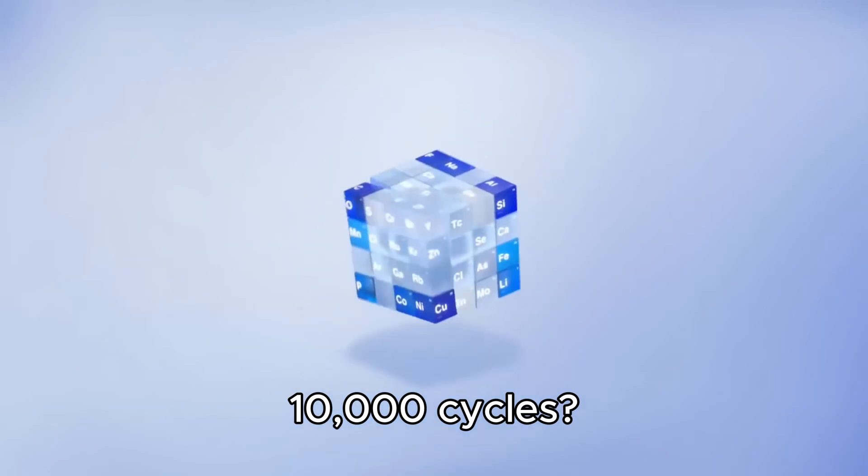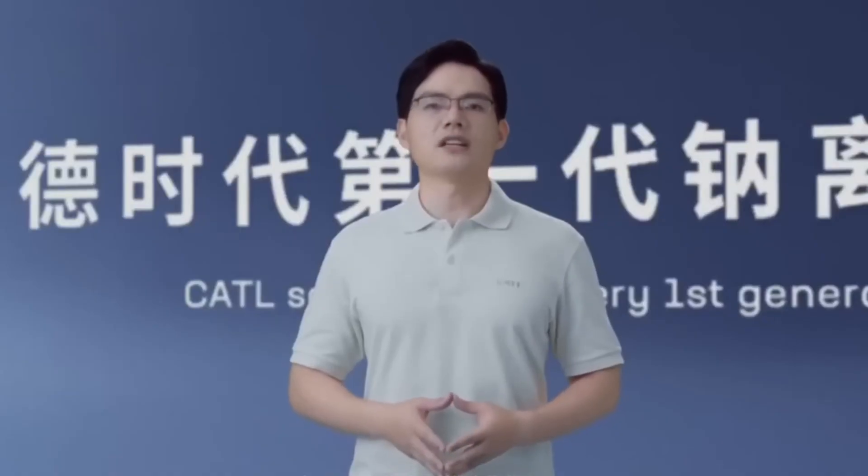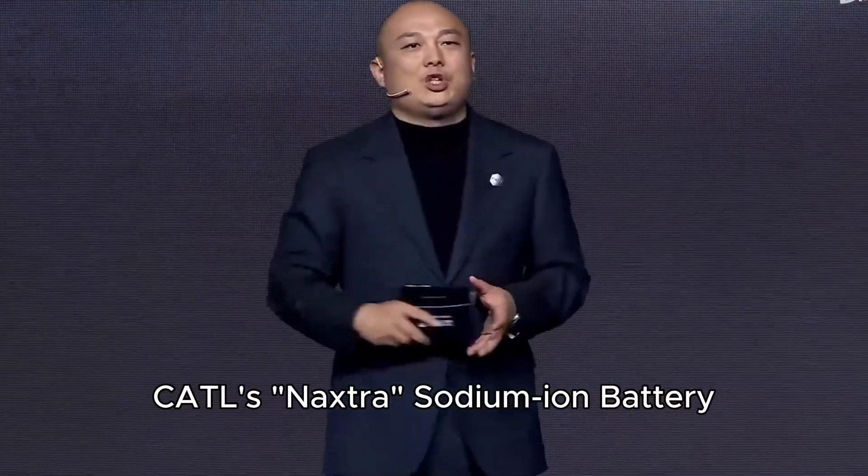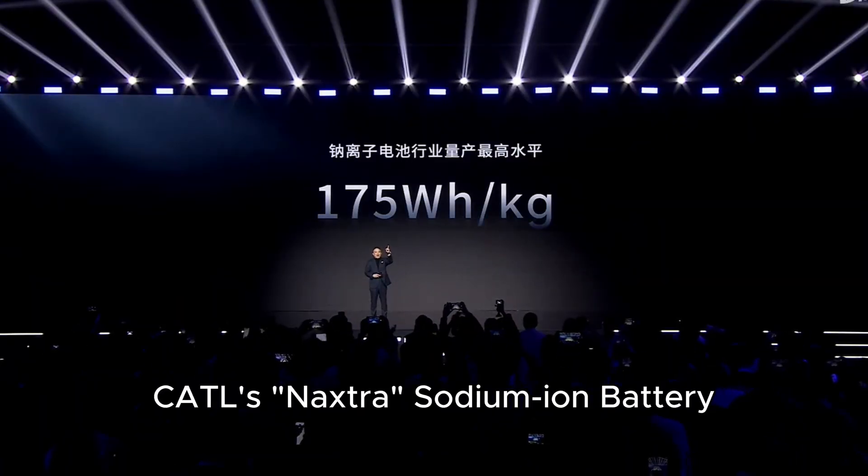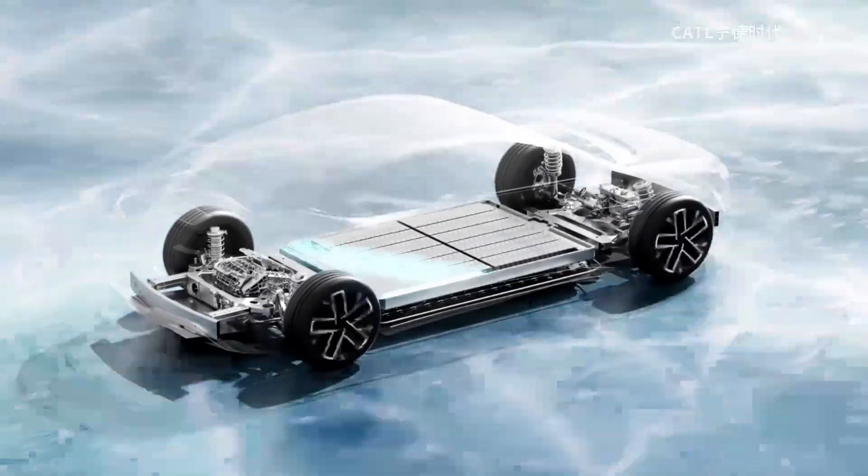Even so, the progress is nothing short of spectacular. CATL first introduced their sodium ion concept in 2021, with cells hitting 160 watt-hours per kilogram. Now, with the newly released Naxtra battery, they've reached 175 watt-hours per kilogram, close to lithium iron phosphate levels, with vastly improved safety and cold-weather capability.